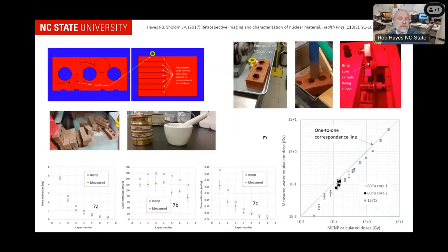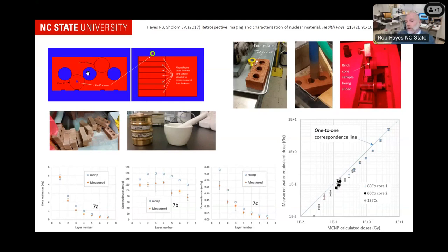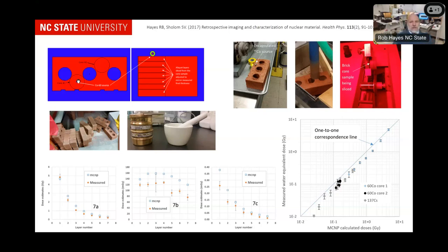Here's an example: I took a brick and put a cobalt source on one and a cesium source on the other. After irradiating the brick, I took it into the lab, did a core, then took slices from those cores. This is an MCNP representation showing the source and the slices of the core underneath it — one right underneath the source and then across from the hole in the brick. So I did a core under the source and a core across the hole, which is a complicated geometry for retrospective dosimetry using ubiquitous building materials like brick.